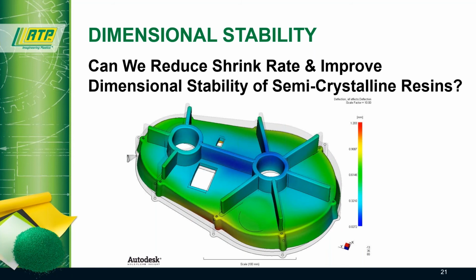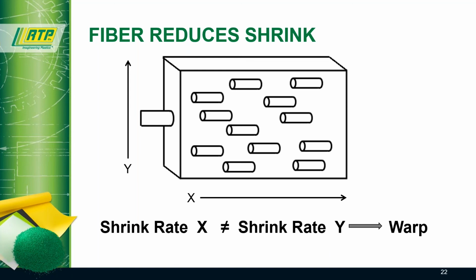The question is, can we reduce the shrink rate of a semi-crystalline resin and make it dimensionally stable? The picture shows how different shrinkage can cause deflection and warpage in a complex part. One way to reduce the shrink rate of a polymer is to add glass fiber. Because glass fibers align themselves in the direction of mold flow, glass fiber will have a tremendous effect to reduce the shrink rate in the direction of mold flow, the X direction. However, they do little to reduce it in the transverse to mold flow direction, or Y. This differential shrink rate leads to parts warping and twisting.